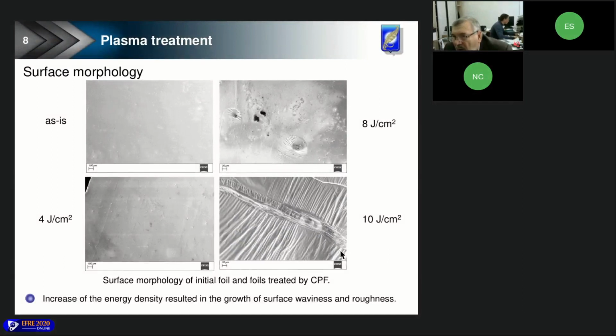Well, the results of surface morphology investigation of foils before and after plasma impact are presented here. You can see that the increase of the energy absorbed by the surface resulted in the formation of wavy surface relief that is characteristic for crystallized melt after high temperature plasma impact. In general, development of different kinds of hydrodynamic instabilities on the plasma-melt border can be the main cause of this effect. For example, the well-known Kelvin-Helmholtz instability that forms at the interface between two horizontal parallel streams of different velocities and densities. In our case, it is plasma flow spreading along the surface of the melt. So vortices at the surface of the melt are formed as a result. They disturb the surface and can look like waves after crystallization.